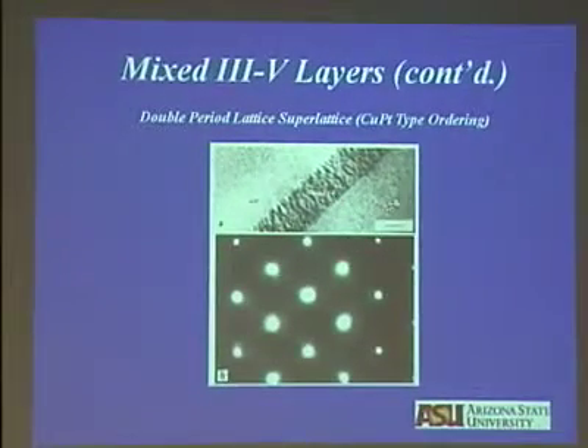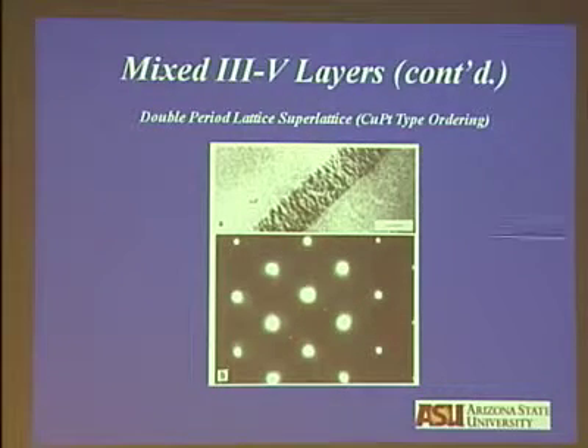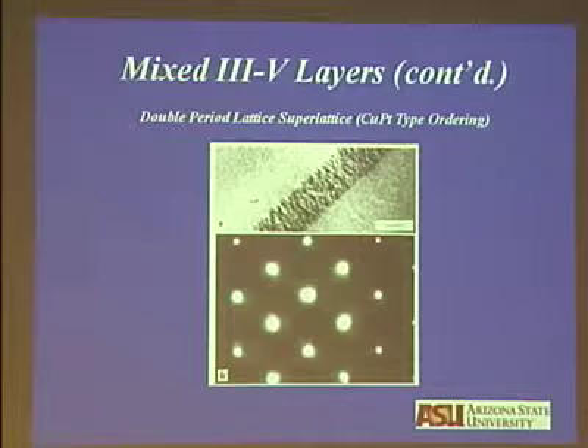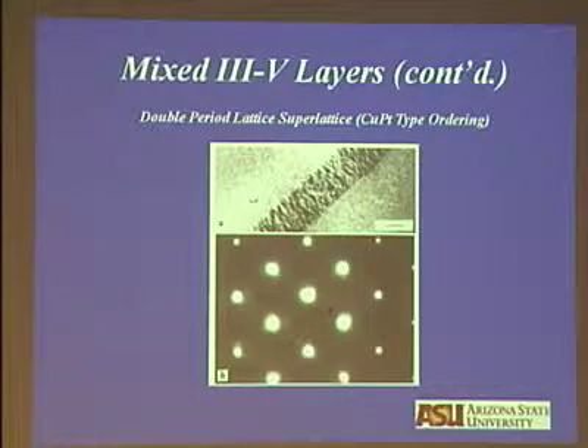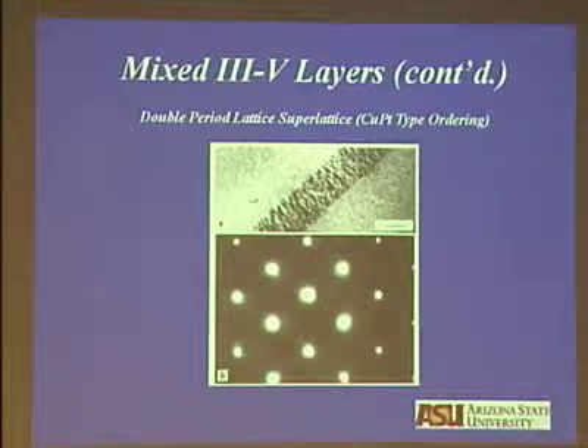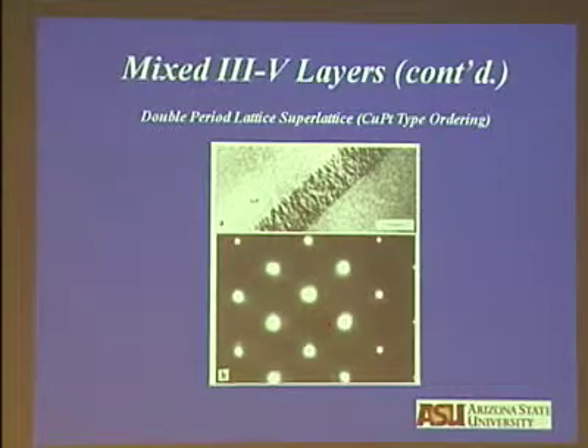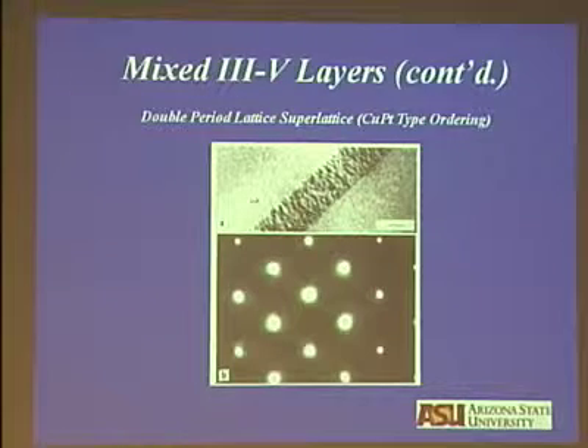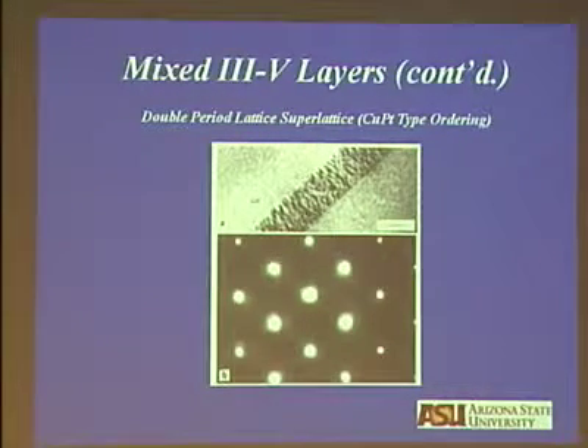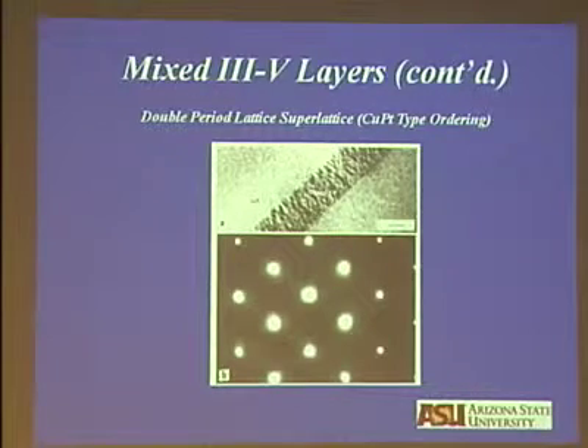Life is not simple. In the same materials, what you observe is an indium phosphide, indium gallium arsenide phosphide, and indium phosphide heterostructure, which we grew by vapor phase epitaxy. The speckle structure is typical of phase separation, and you have a 110 section. But in addition, you see spots at half 111 positions. So the periodicity along the 111 direction gets doubled as a result of ordering. So there is ordering coexisting with phase separation in these layers.